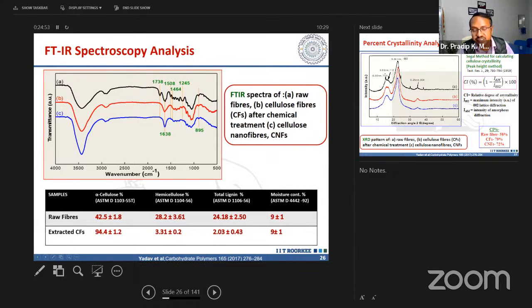I can confirm that though I am claiming there is no lignin, as far as the chemical analysis is concerned, I have seen it is 2.03%, so lignin is still there. But for our target application, this 2.03% is not too high to hamper our application. So I'll be continuing with the cellulose, hemicellulose, and lignin content of this material.